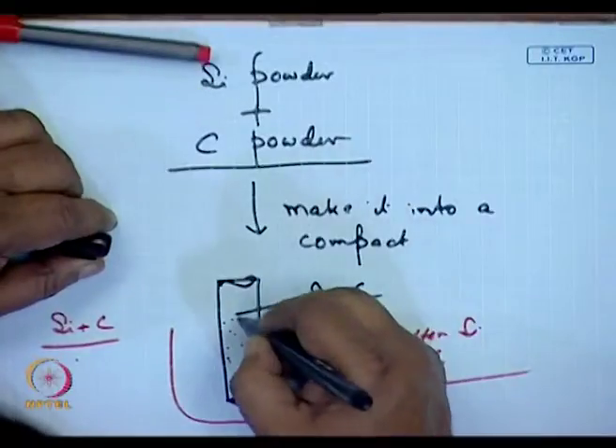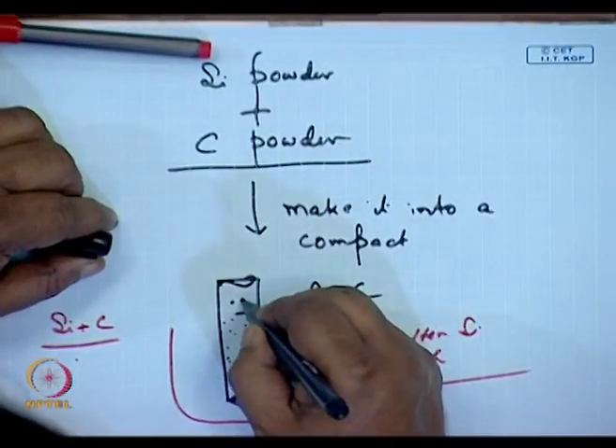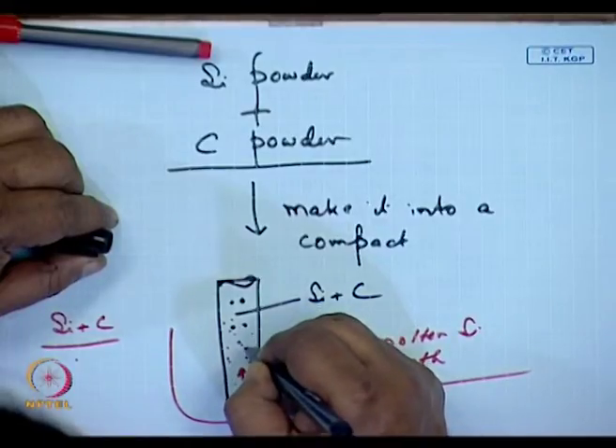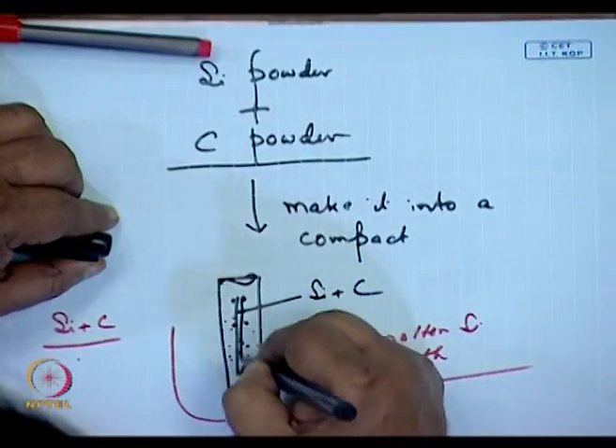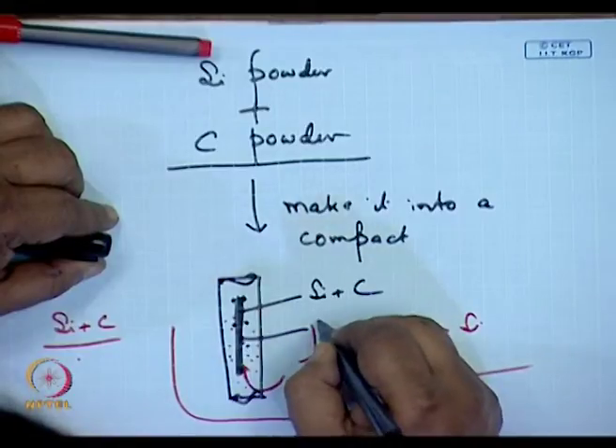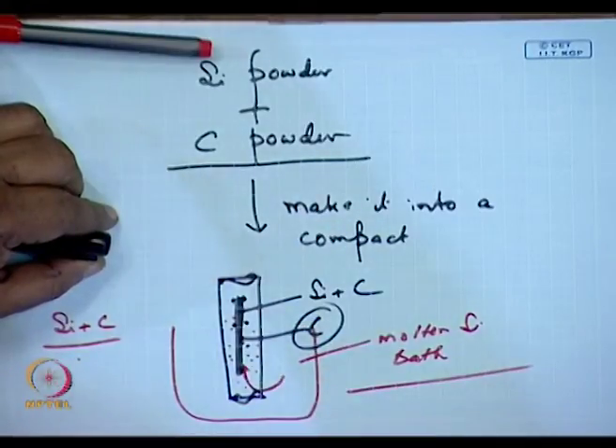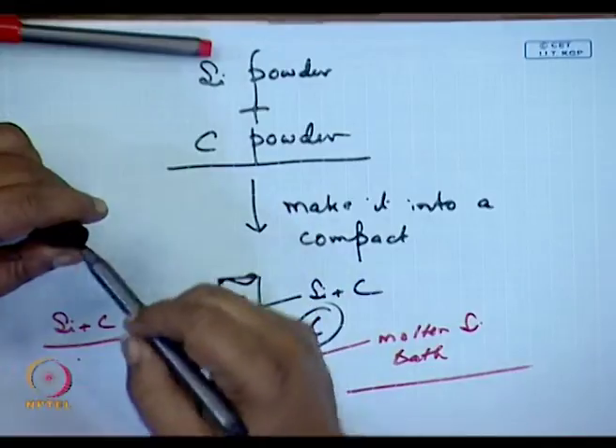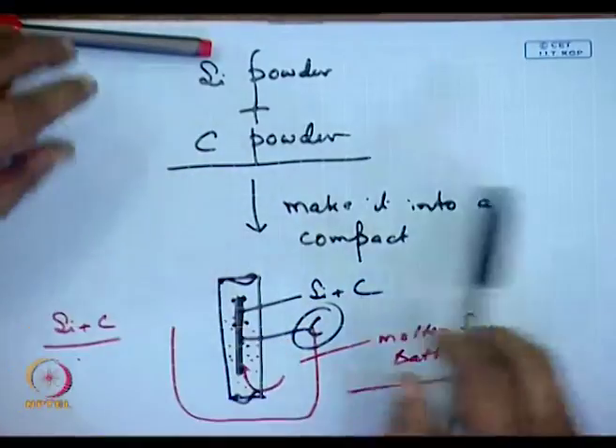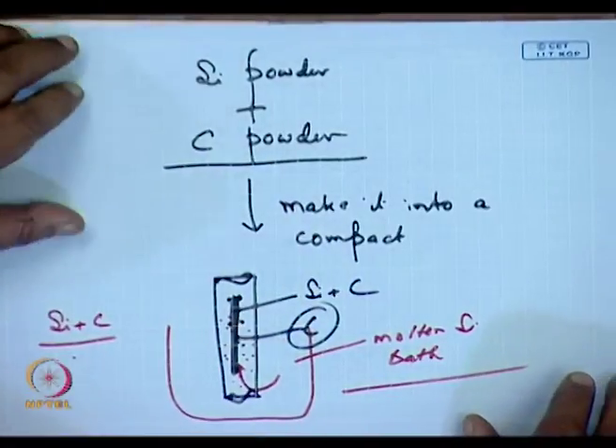One of the biggest problems that we find in this sort of sintering is that we are frequently left with unreacted carbon. There is a center part, the carbon remains unreacted. Now, this also can be avoided if we take proper precaution.